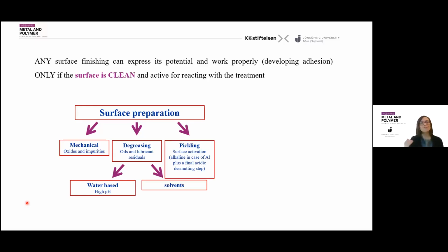Then we go to the final step, the activation step, pickling. The surface activation is a chemical solution designed depending on the substrate. In the case of aluminum, it's very commonly an alkaline pickling that could be followed by even an acidic desmutting step. So even pickling can be broken down into several steps, and all of these will prepare the surface to be really active.